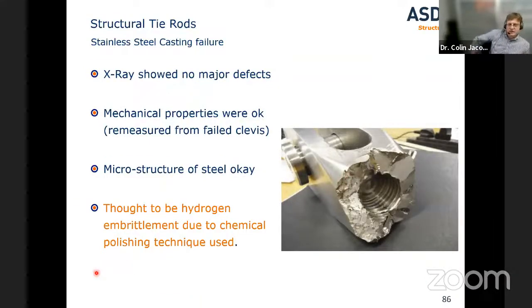Another failure we've seen in the field is a stainless steel casting failure. This is quite unusual, where the product was investigated and it was found to meet all properties, met full specification, absolutely nothing wrong with it. Even down to the microstructure of the steel looks good. And so the only thing we could attribute this failure to was hydrogen embrittlement. So the supplier in this case had polished a fork using an electrochemical process. He didn't achieve the desired result first time, so he put it through again. Again, it's a hydrogen-based process. This introduced more hydrogen, so it's thought that's what led to this brittle failure through the casting. So again, it's very important to realize that your post-processing can often have a catastrophic effect on some of these castings.